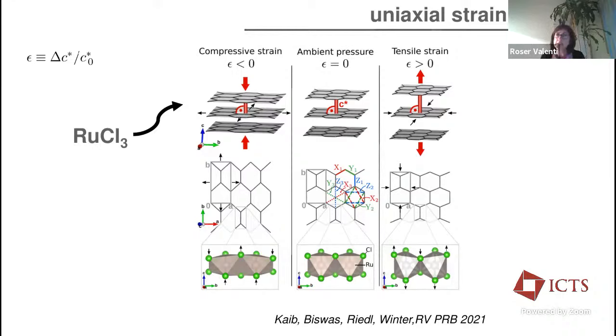Another way of applying pressure, in the sense of going to this spin liquid region, is to apply uniaxial strain. Because when you apply uniaxial strain, basically you are expanding this honeycomb lattice, and the expansion of the honeycomb lattice is going to get rid of these direct hoppings, which is what is harming your being purely Kitaev. So what we did is simulations of these different types of strains, either compressive or tensile.